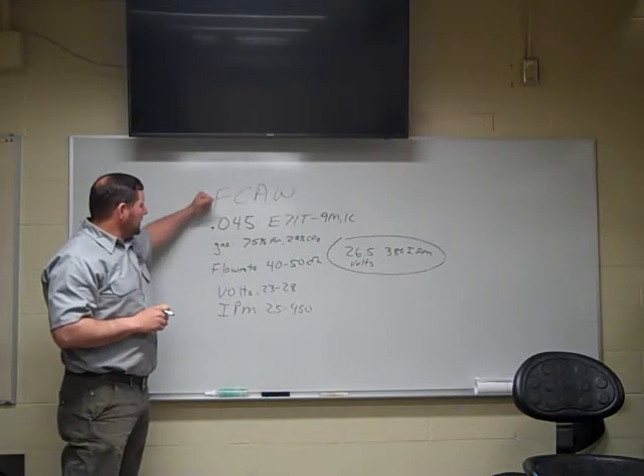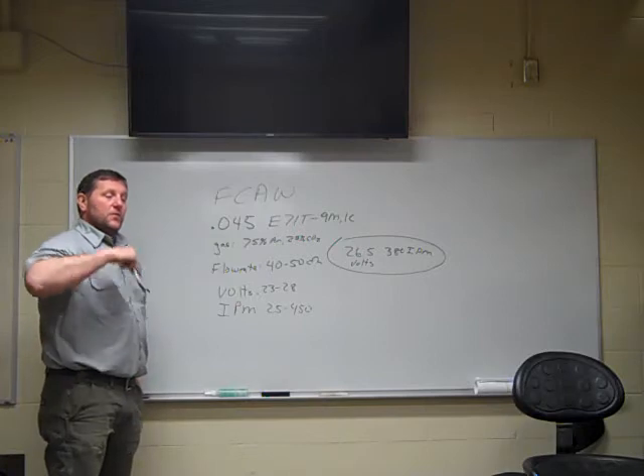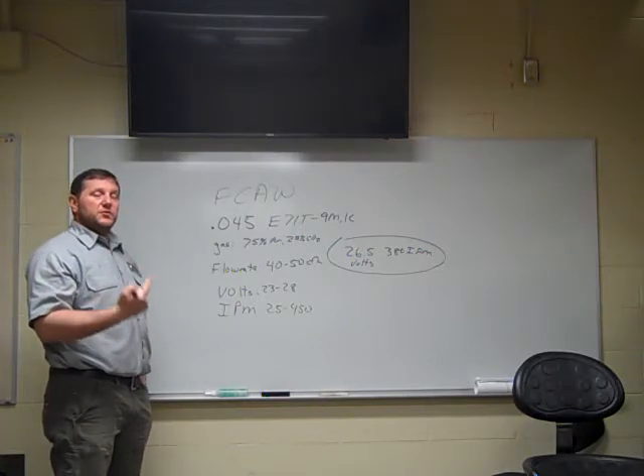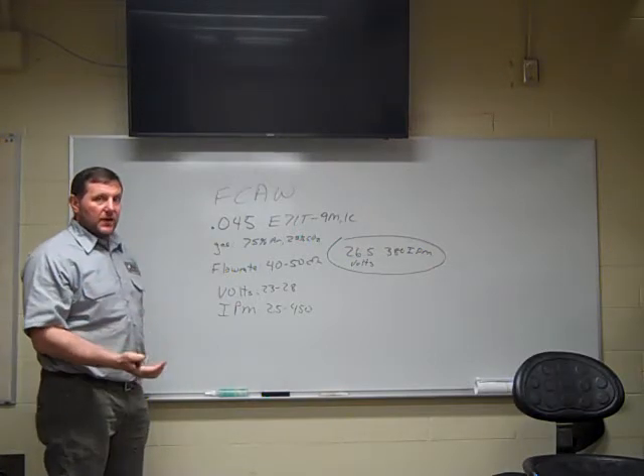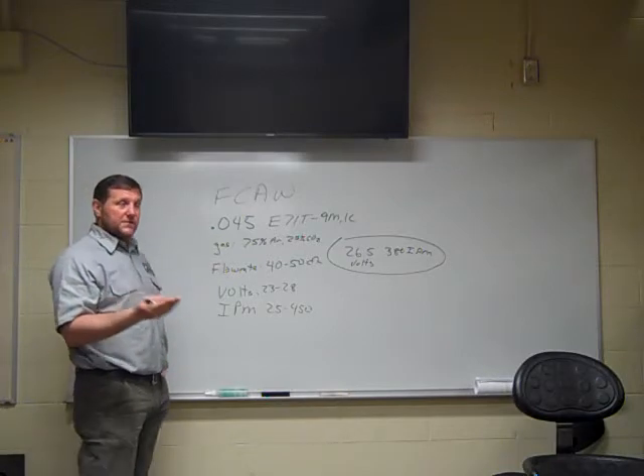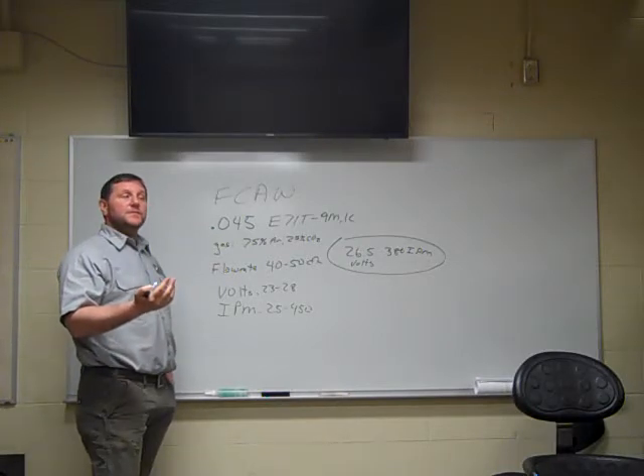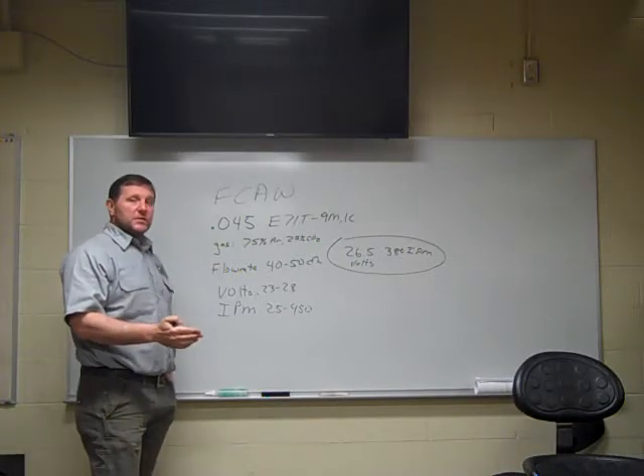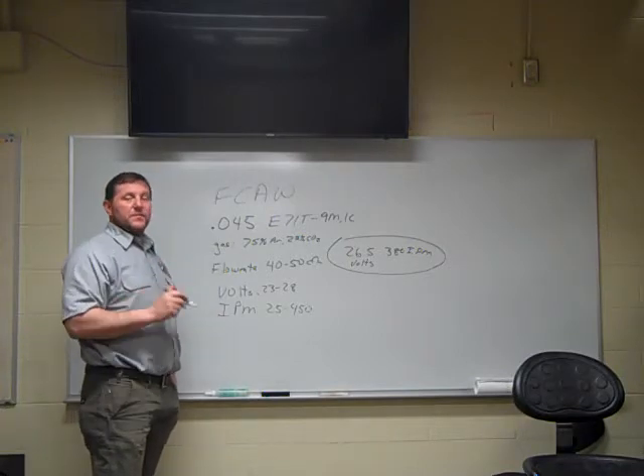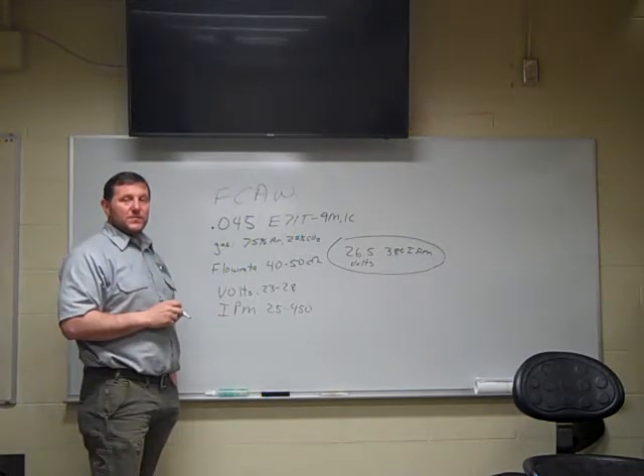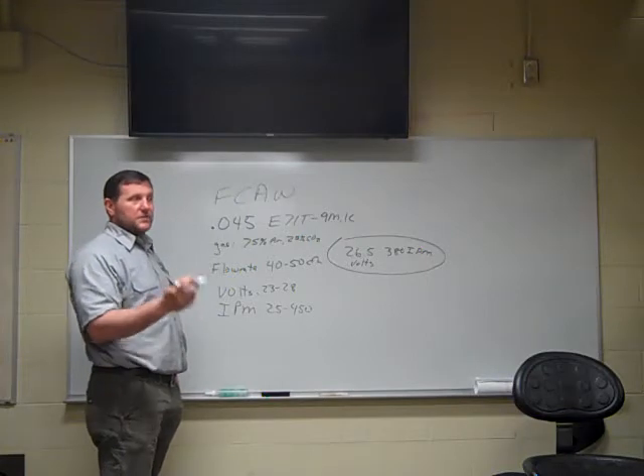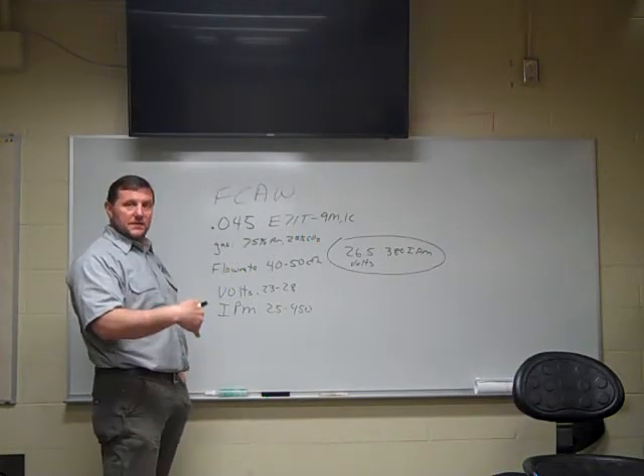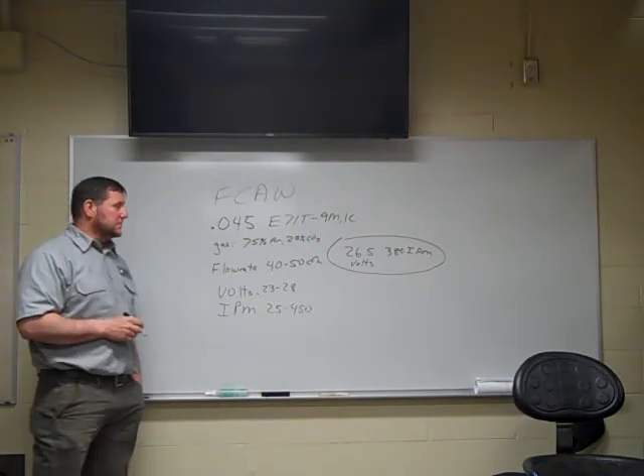Now, flux core, like I said, when you start doing multi-passing, make sure you clean that flux. You might have to grind the toes of that weld, even when you're doing your bend test. It's got to be super clean. Get that slag off there, make sure it's super clean before you put your next pass on. You can't weld right on top of that flux. It's going to cause you to have slag inclusions.